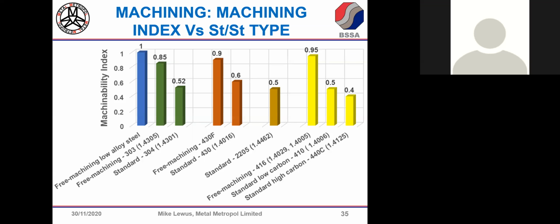But you'll see here standard grades have significantly lower machinability indexes compared to low alloy or mild steel. If we use that as the base, low alloy carbon steel, the blue bar with 1, you'll see that something like 2205, a duplex grade, it's cut by half. 304, similar, 0.52 compared to 1. So sometimes you just have to learn to live with the difficulties, but be particularly mindful of machining parameters.